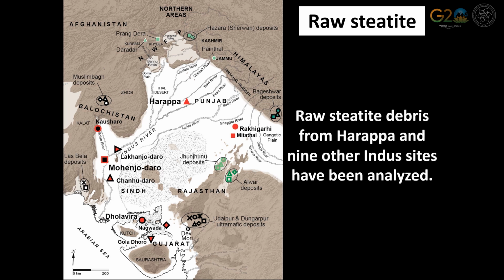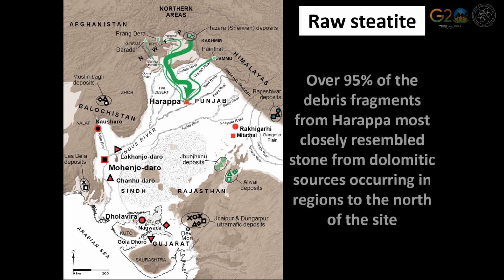Raw steatite debris fragments and the occasional unfired steatite artifact from Harappa and 9 other Indus sites have been analyzed. These additional sites include both urban centers and lower order settlements in Haryana, Sindh, and Gujarat. The largest artifact set comes from Harappa. Over 95% of it appears to have come from multiple dolomitic steatite deposits occurring across a zone between 300 to 400 kilometers north of the site. With regard to Harappa, this is not completely unexpected, as these are the sources nearest to the site.